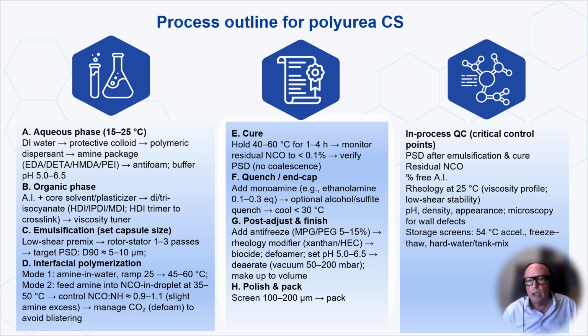And this is crucial. This step sets your capsule size destiny with target D90 around 5 to 10 microns. The magic happens during polymerization, where you manage that critical NCO to NH ratio of 0.9 to 1.1. Finally, post-cure and quench with monoamines like ethanolamine to consume residual NCO groups. Then add finishing touches: antifreeze, rheology modifiers, biocides.